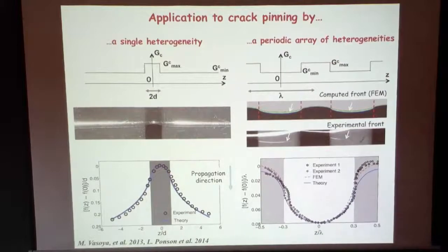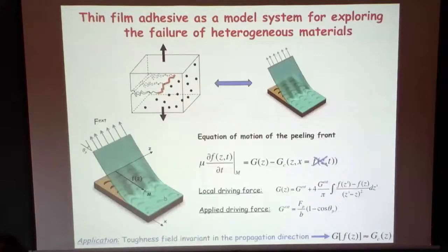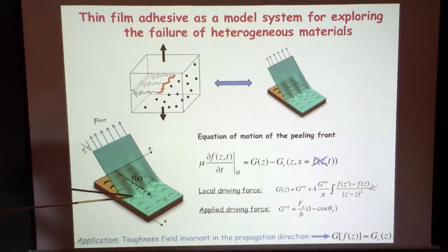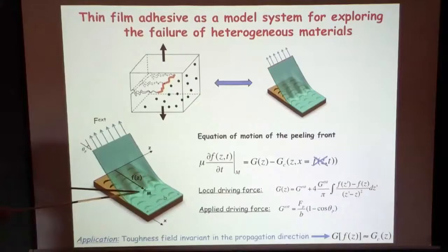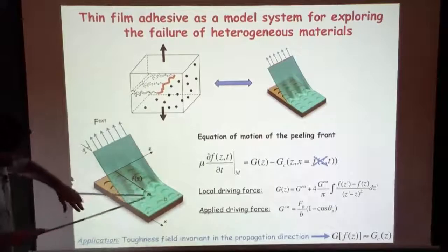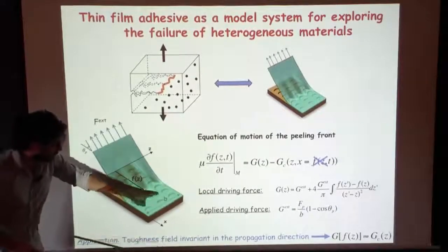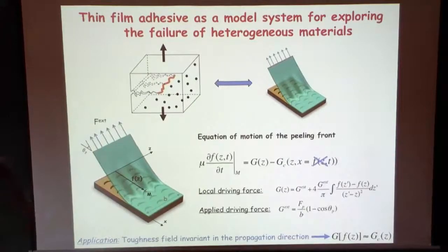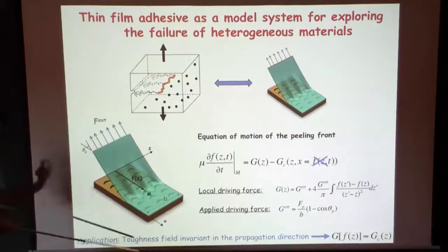In the elastic term, I'm confused why the thickness of the adhesive and the substrate didn't enter. Shouldn't that be a cutoff on the kernel? Yeah. But that's a good point. It's a different source here where the dominant elastic contribution comes from. Okay, you have the driving force here that inputs some energy into your system. You have stored energy, elastic deformation energy stored in your system as bending energy. You see these wrinkles here. They are the ones storing the energy. These are the ones that cost you energy to deform more here than here. So the substrate is rigid. You have a wrinkling elastic plate, and you can use bending theory to calculate the excess of energy you need to pay in deformation to deform it like that, and calculate the driving force.